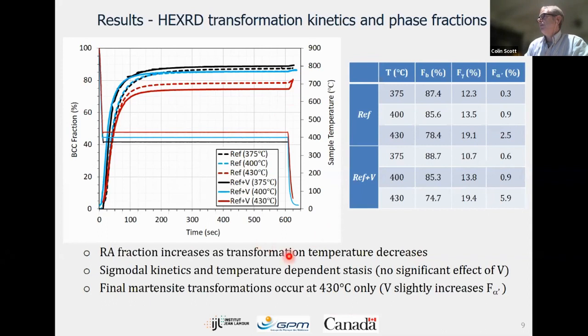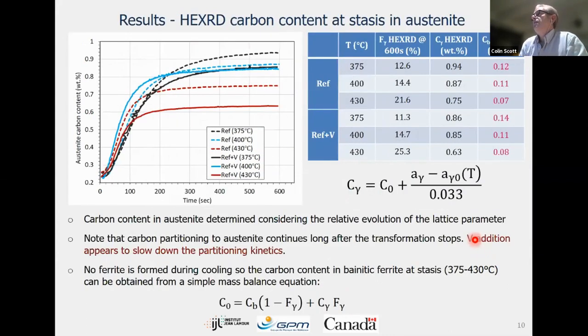I think that's probably everything. So this is the data from, you can see, you actually see the numbers there. And here, now we're looking at the carbon content in the austenite. So we get that directly from the austenite lattice parameter. And using this simple equation here, it's well known. And you can see quite a few different things in this graph.